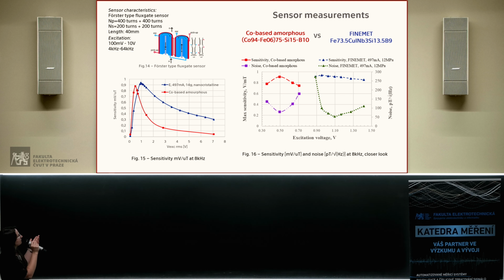So after this, the goal of getting at least a bit better magnetic material than co-based amorphous is reached, because before there was a stereotype that co-based amorphous magnetic material is better than Finemet. But at least we can show that it is not better. It could be the same or worse than Finemet. So we are going in the right direction.